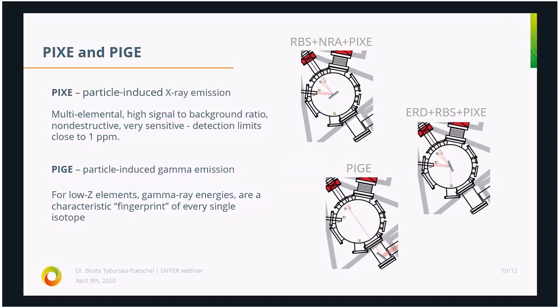And then still some assisting techniques. One is particle-induced X-ray emission. Simply, when a beam is entering the sample and is coming by atoms, then the electrons are getting excited, and mainly K and L shell electrons are being ejected from the sample, and then electrons from the outer shells are trying to fill this gap and falling to the lower shells, producing X-rays. And those X-rays are characteristic for each type of element, and you measure those X-rays, and this is how you use this technique.